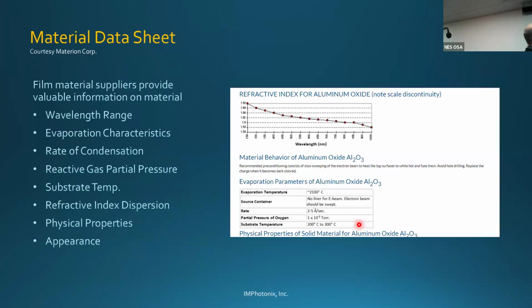Okay. This is where the material vendor data sheets are very important. If you look at this top graph here, it gives you the dispersion of that material. So what we do with TF Calc, and I'm sure it's the same with FilmStar and McLeod software, is you take a material, you define it, and you put in the dispersion values so that when you design the coating, that software knows, oh, I'm running between, say, 190 and 350. I'm going to be using 2.5 as my index of refraction for that material. So it has a lookup table that it'll refer to for the range that you're actually designing that coating for.